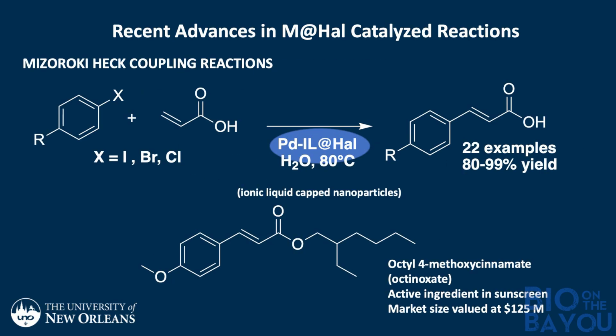Now, we have additional catalysts that we have developed, and essentially this is our latest one. This is an ionic liquid palladium system that essentially allows for Heck coupling. This reaction produces these cinnamic ester types of intermediates, which are prevalent in things like sunscreens. And so this chemistry again can be done completely in water. We haven't quite finished the recycling experiments, but at least so far we've gone through 2 or 3 cycles with this material. And so overall, this has a high level of reactivity, much higher than the catalysts currently used for these type of reactions.